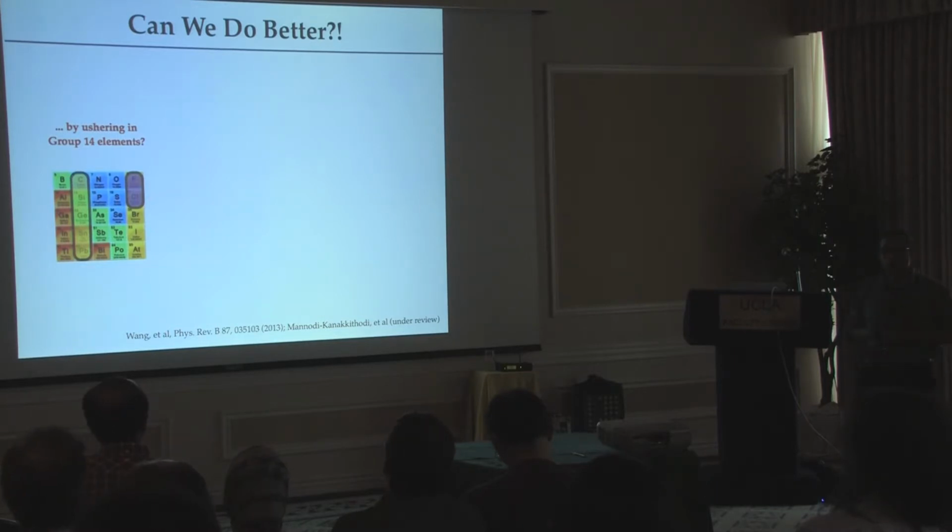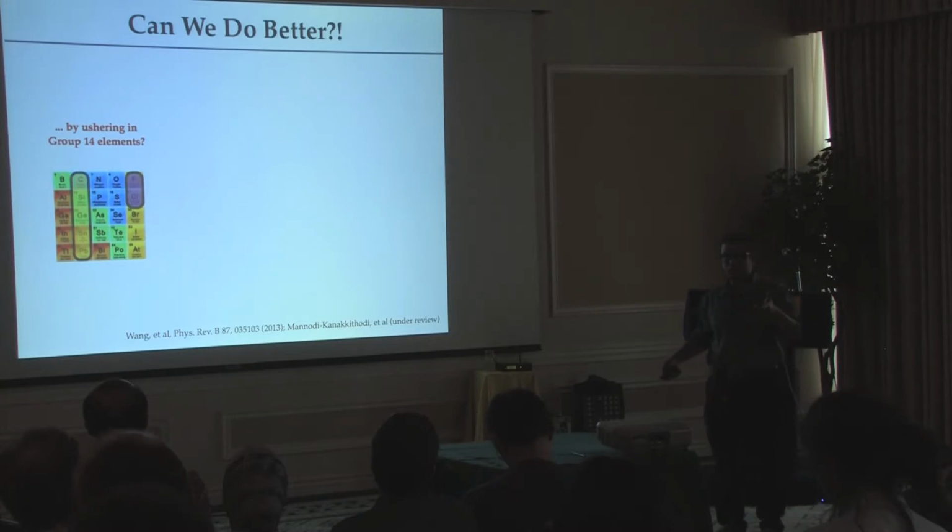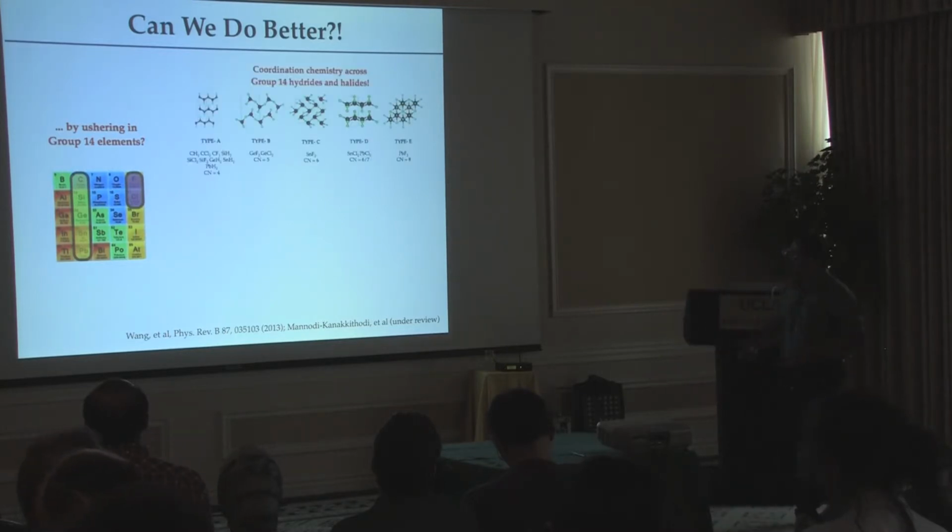And you also go from insulators, from a classic insulator to a good metal as you go down the column. So the question is, if we start replacing carbon with silicon, germanium, tin, etc., are we going to see something interesting? And hydrogen in our conventional hydrocarbon, if you replace the hydrogen with fluorine and chlorine, maybe we can exploit the ionic part of the dielectric constant. So we began to do this kind of a basic study.